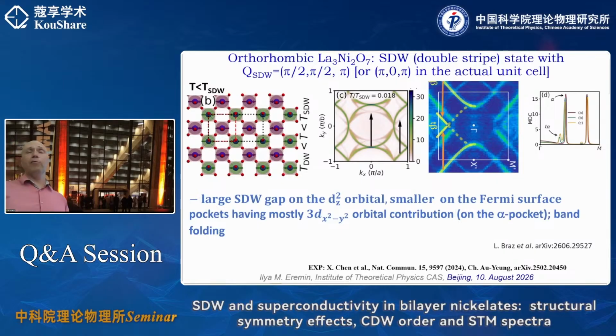Whereas if you start from a 3-spin polaron and Zhang-Rice singlet, you start from scratch essentially, and you have to explain what is the symmetry of the gap, why this superconductivity occurs. While if you start with the pictures that I presented, which is based on an initial guess from DFT plus correlation, it somehow makes a lot of sense to you, no?